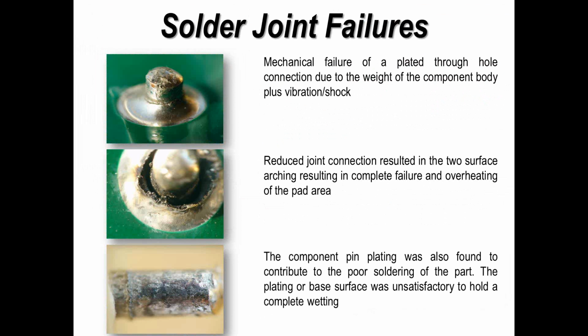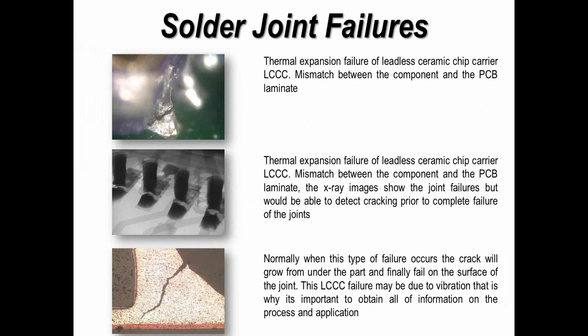This example is kind of a combination of mechanical failure and then obviously having a high resistance causing it to burn out. So what you can see here is a very heavy component was actually vibrating on a printed circuit board, and in time it actually started to form a crack around the termination, and then in time, because of the operating voltages, it actually burned out the printed circuit board. So it's all about the weight, the component, and its capacity on the board, and not using the right design rules.